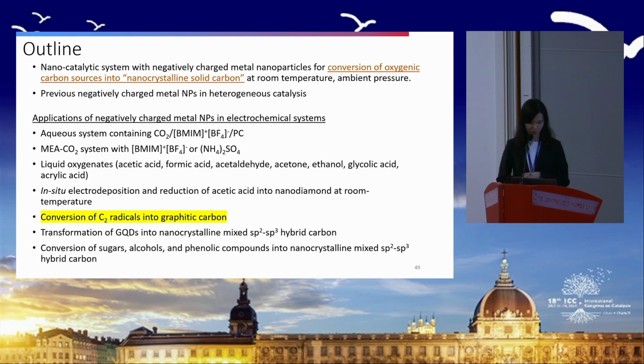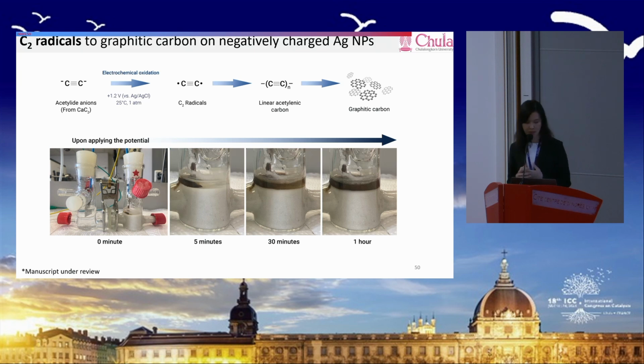Okay. Now we try to look further at what happened with the C2 radicals that we saw from our Raman spectrum, which are a part of our product as well. In this experiment, we generate C2 radicals by electrooxidation of calcium carbide, and then apply them to our negatively charged system. And here I missed the pictures, but actually we end up having graphitic carbon from C2 radicals, both in the electrolytes and also on the electrodes.